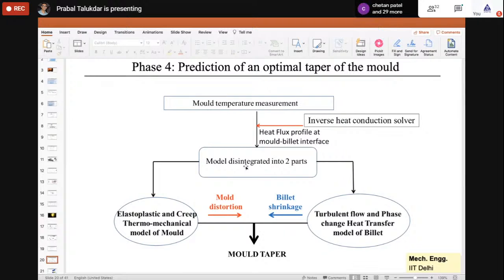Then we divide the problem into 2 parts. One part, we do an elastoplastic and creep thermomechanical model of the mold. That means this gives us the deformation or distortion of the mold. And second part, we do a turbulent flow and heat transfer analysis of the billet, and from that temperature result, we do a billet shrinkage analysis, right?